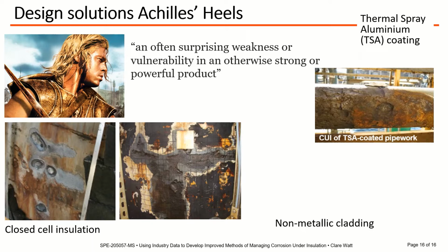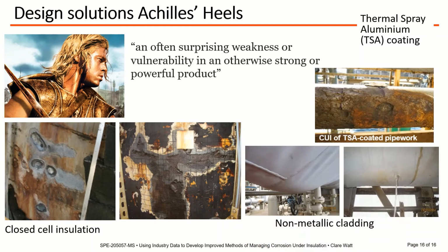On the left, corrosion rates of 2 millimeters a year being reported, and on the right, maximum cumulative metal loss of 11.5 millimeters over 6 years in service. Finally, drain holes are especially important to apply for non-metallic cladding. However, we don't believe that any of these Achilles heels or the conditions that trigger them are sufficiently widely understood. But the good thing is they could all be avoided to maximize the value of these products, to slow down CUI, or at least not to make it worse.